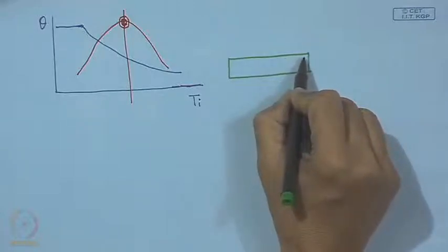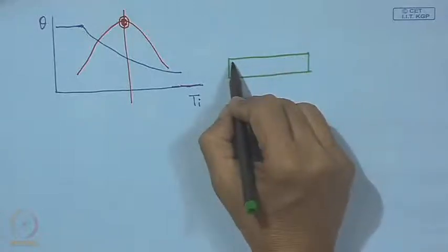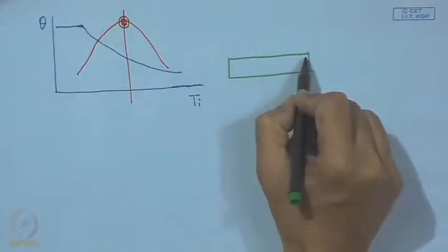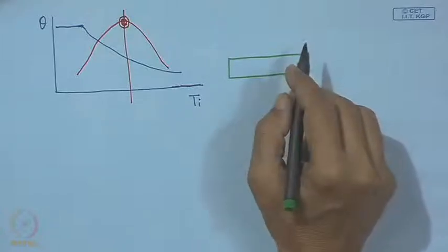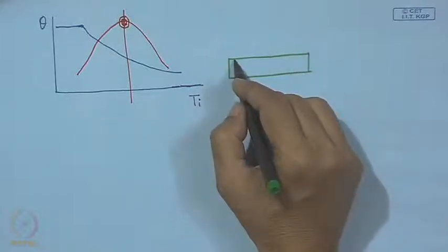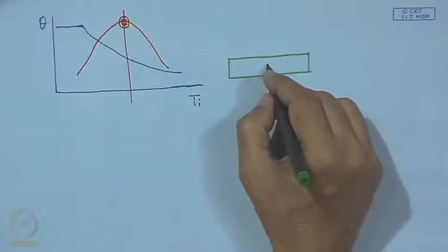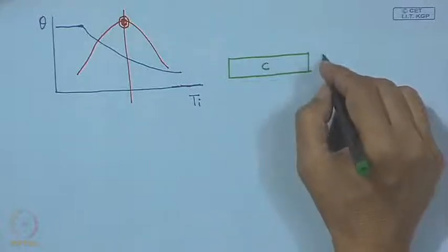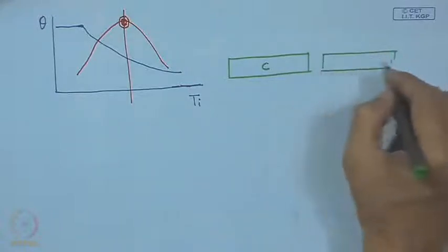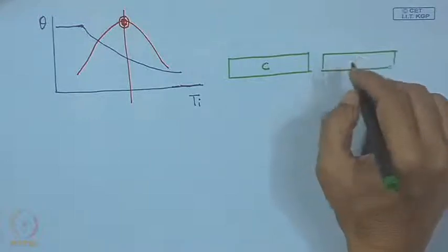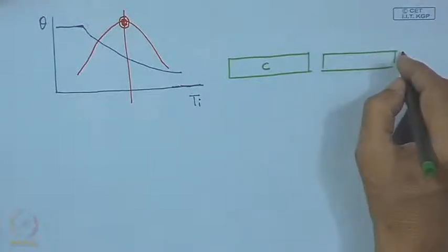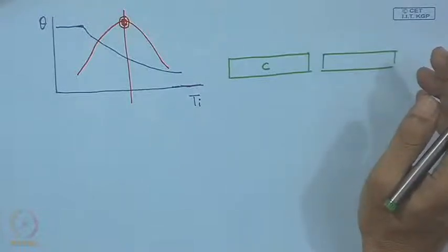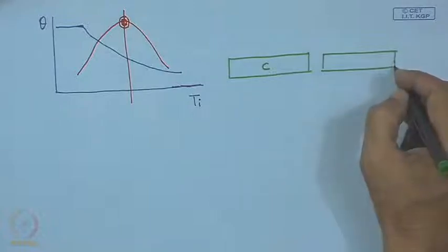It is a continuity of the layer, and titanium should be continuously, uniformly distributed over the entire wetted surface, so that we have carbide formation in case there is a source of carbon. If it is an oxide ceramic, then it should be titanium oxide. If it is a nitride ceramic, most likely it should be titanium nitride.